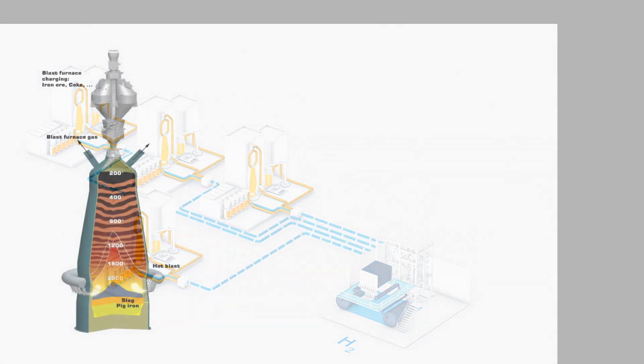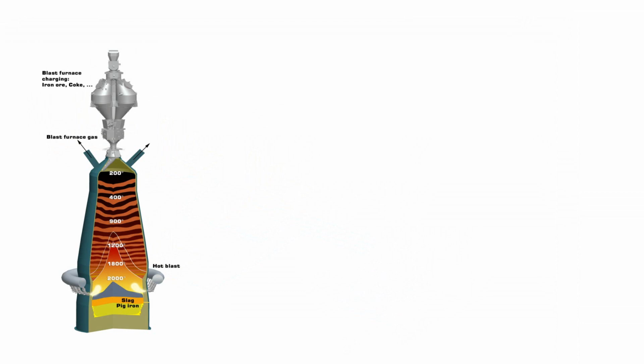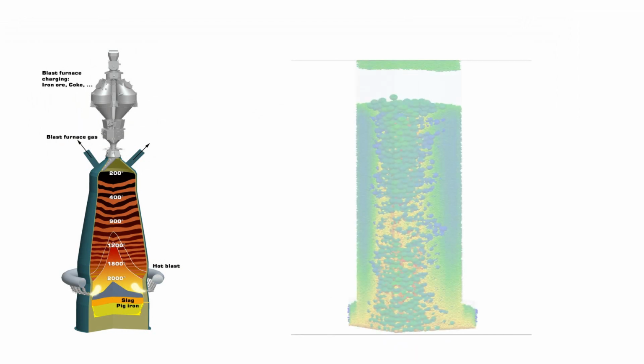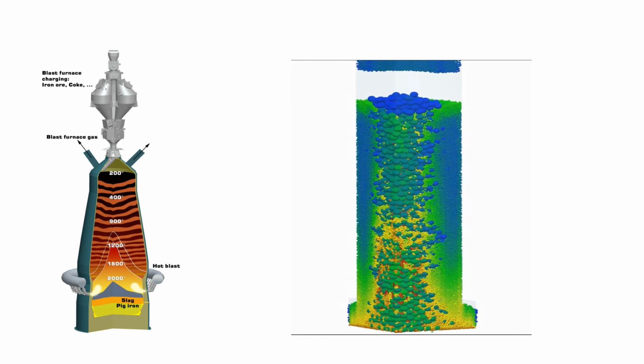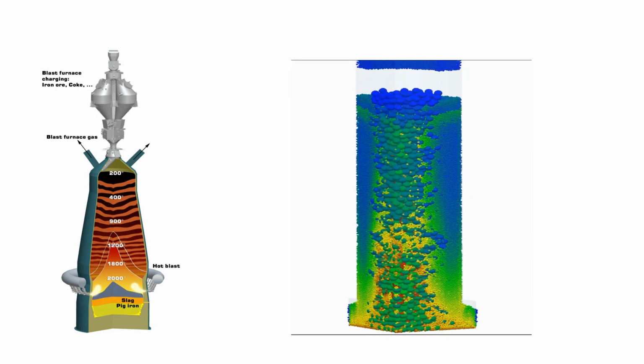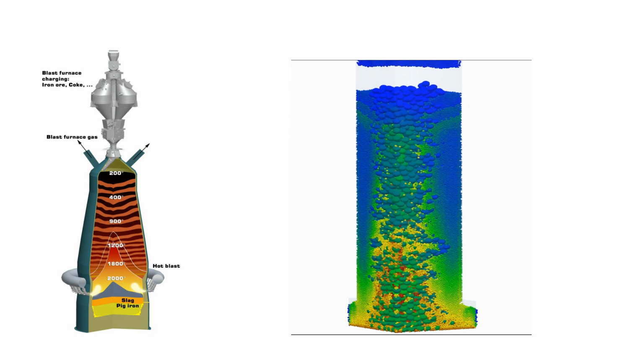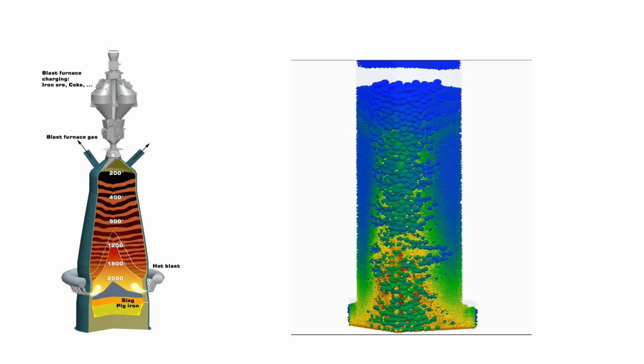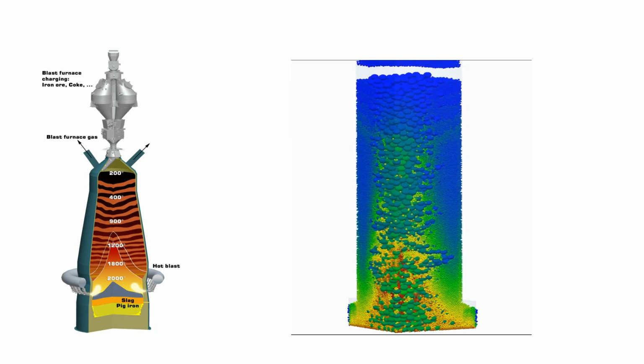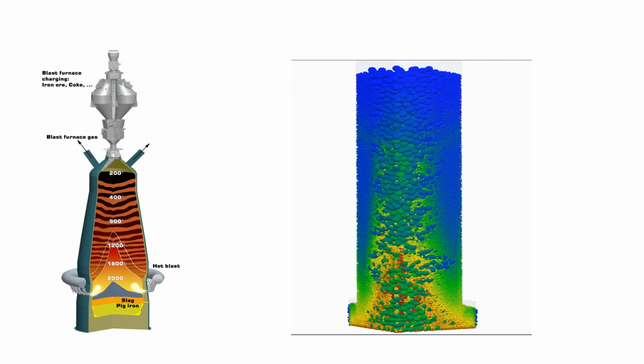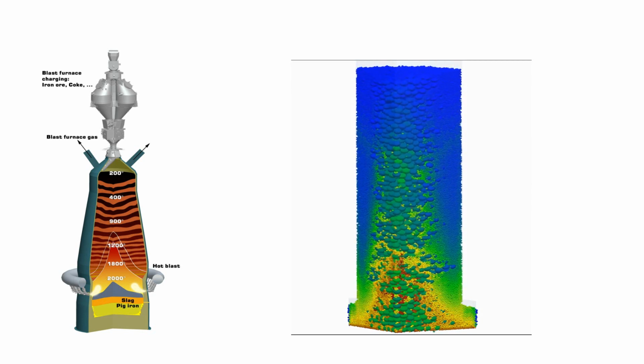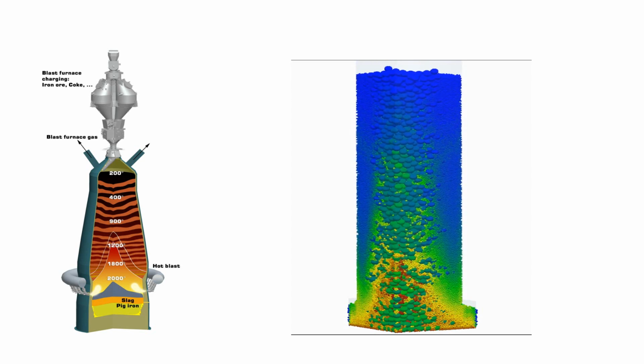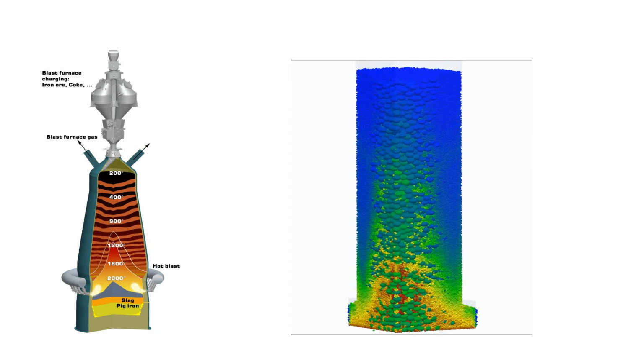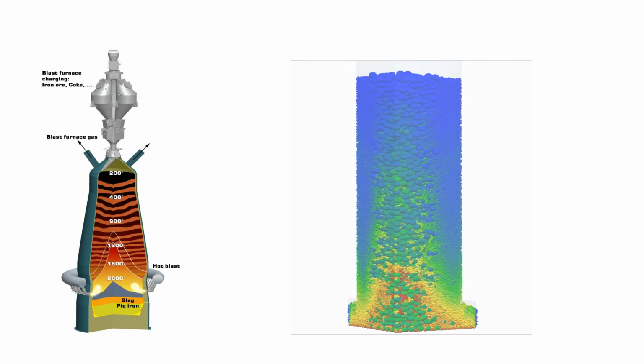However, in a blast furnace, coke is generally required, to lend the furnace its permeable inner structure, allowing gas percolation, as well as slag and metal tapping. Therefore, in a blast furnace, only a fraction of the ore reduction can be achieved by hydrogen. Current pilot plants also use coke gas for this, as it can contain up to 65% hydrogen and more than 20% methane. Details of the interplay among carbon monoxide and hydrogen in the reduction reaction are currently under investigation, and will be discussed in a separate class.